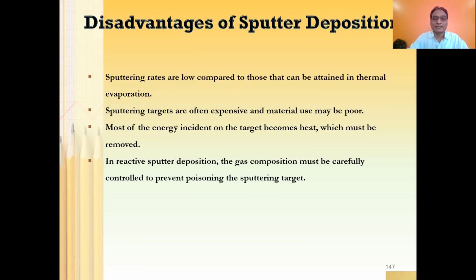Sputtering targets are often expensive. Most of the energy incident on the target becomes heat, which must be removed. That is why water cooling is very, very important. And in reactive sputter deposition, the gas composition must be carefully controlled to prevent the poisoning of